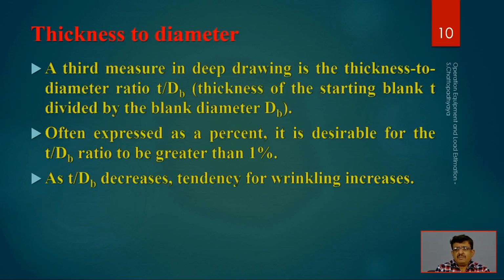The third measure, apart from the drawing ratio, is the thickness to diameter ratio, often expressed as a percent. It is desirable for the T by DB ratio to be greater than 1%, so T cannot be very thin. It should be at least 1% of the diameter of the blank. As T by DB decreases, the tendency for wrinkling increases. So the thicker the material, the easier it is to go for deep drawing. Otherwise, unintended marks, wrinkles and maybe surface tears will come. So this is also a very important ratio, the third ratio we have discussed, T by DB.